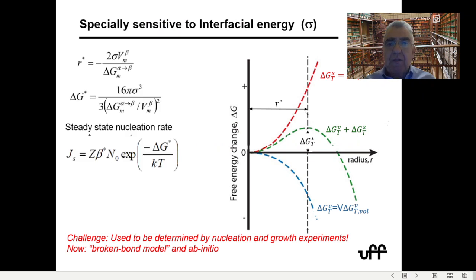If you look, for instance, at the interfacial energy, all the formulas for critical radius, for the critical barrier for nucleation, they all depend on the interfacial energy. So this is the critical parameter. And unfortunately, if you look at the literature, they used to be determined by nucleation and growth experiments. So it's kind of a real bad cycle. Now the softwares are using these broken bond models and ab initio calculations to try to solve this.